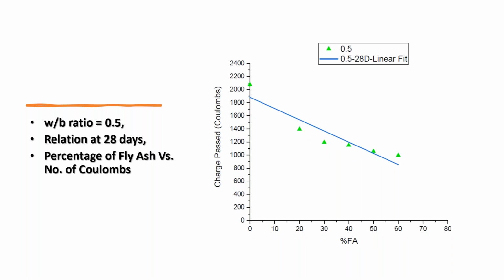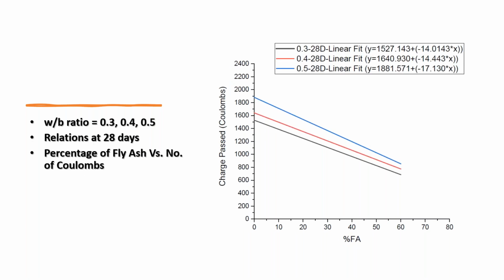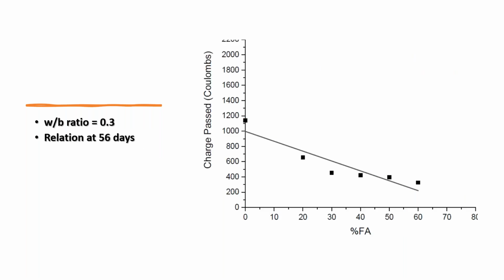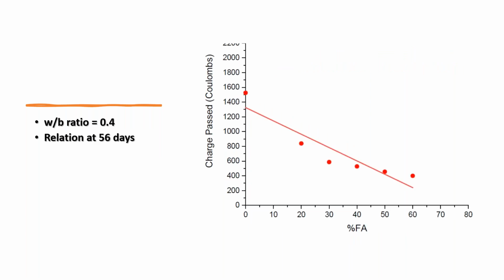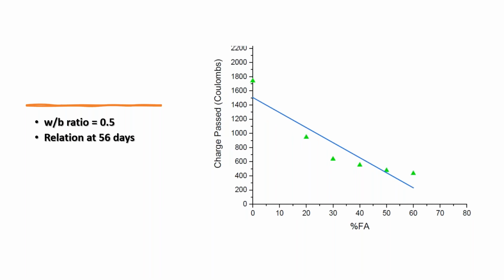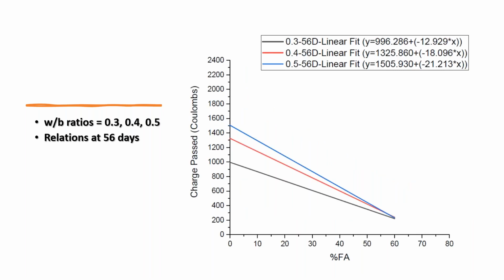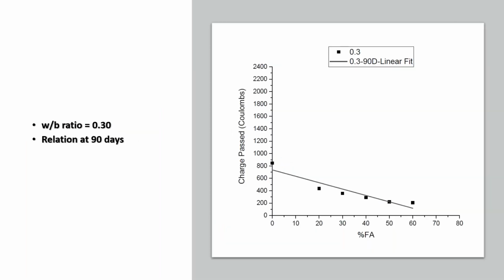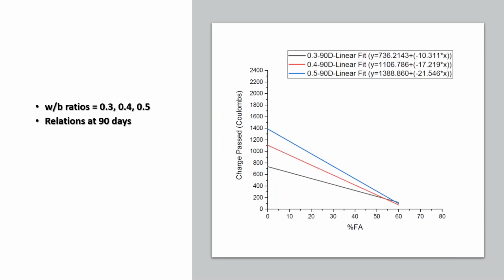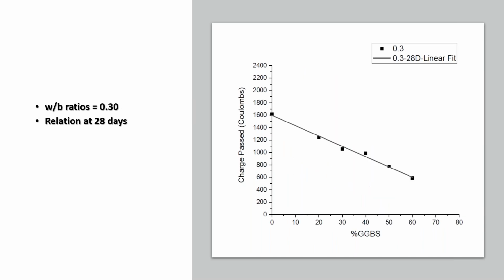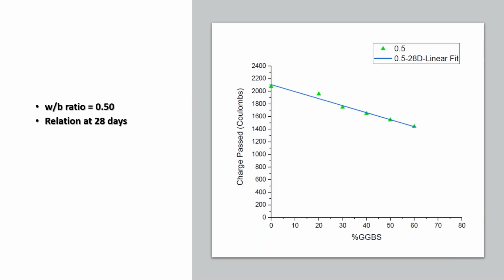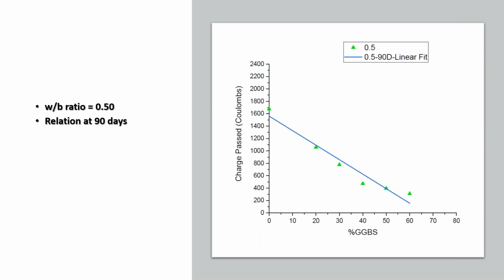And we're trying to give certain equations for them. And all the three graphs combined together for 0.3, 0.4, 0.5 at 28 days. And 0.3 at 56 days, 0.4 at 56 days, 0.5 at 56 days. Then all the water binder ratios together at 56 days. Again, 90 days, 0.3, 0.4, 0.5 at 90 days, and all the relations together at 90 days. That earlier case was the fly ash, now it is GGBS. We can see similar graphs for GGBS at 28 days. I'm just quickly going through them.